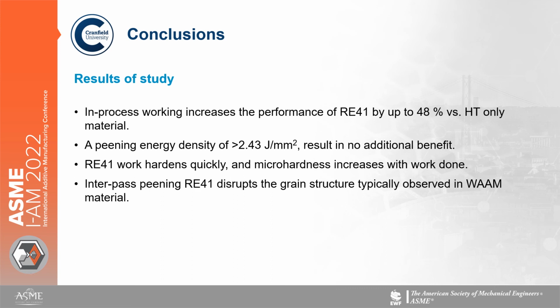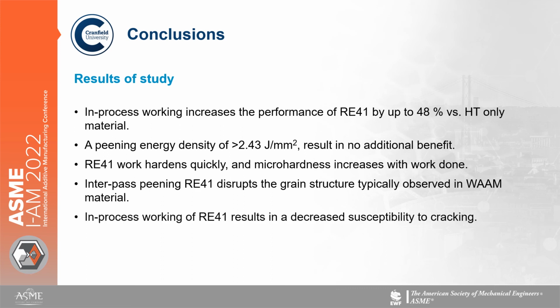And the interpass peening of Rene 41, as we saw, disrupts the grain structure typically observed in WAAM, and we saw quite a significant difference in the texture of the material. So we found that in-process working of Rene 41 results in a decreased susceptibility to cracking, because we didn't find any cracks in our worked material. And we think that might be due to the relaxation of the strain introduced during welding.